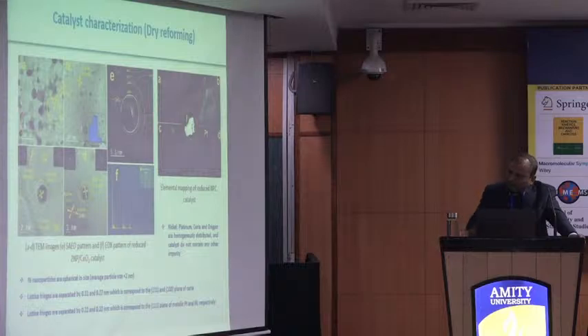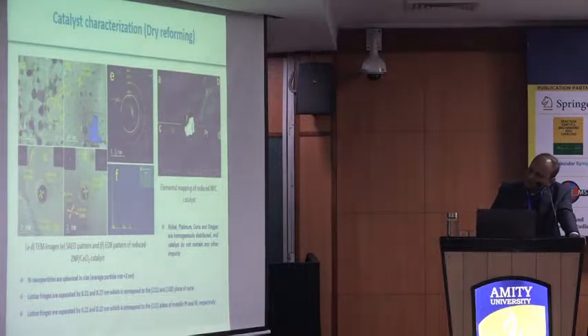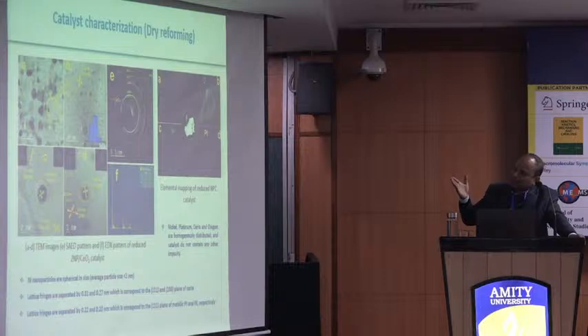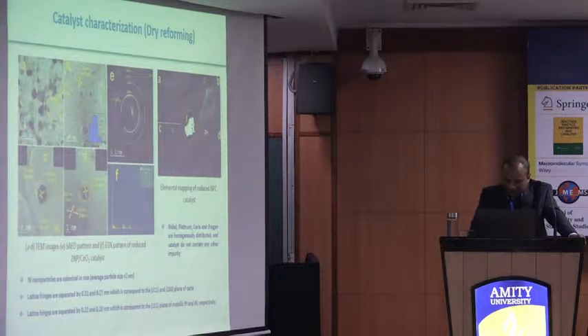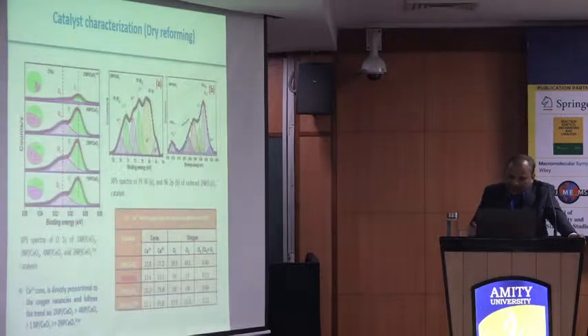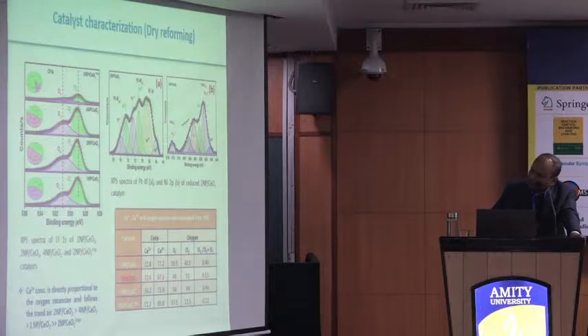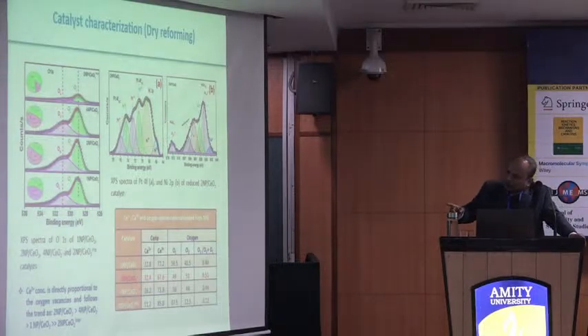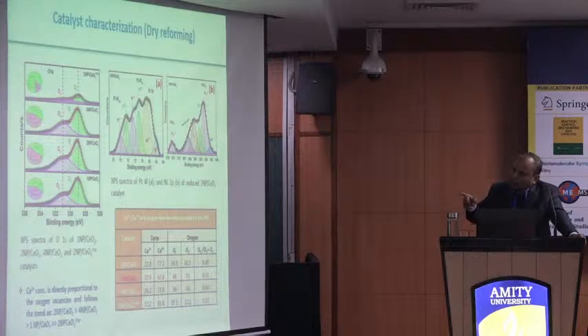And these are the TEM images of the catalyst. Here we can see that platinum and nickel are highly dispersed, and also a homogeneous distribution can be seen from the TEM elemental mapping here. And also we have done some XPS. Here also you can see that for our 2NP ceria catalyst, the concentration of Ce3+ is high for this catalyst, and this is the reason that this catalyst is showing very high activity.